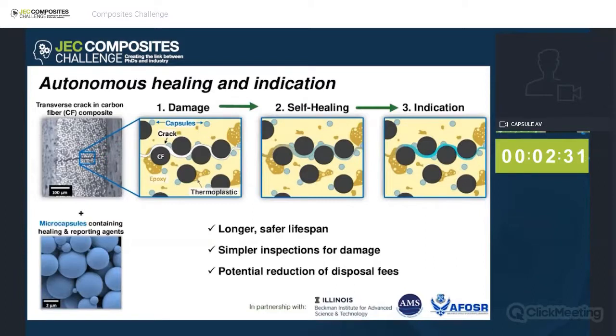From my slide, you can see that self-healing and damage indication begin immediately upon damage in this material system. As cracks propagate, the embedded capsules will burst and release their liquid cores. Then the released solvent will dissolve local thermoplastic, distribute it into the damaged areas, and finally evaporate to leave solid thermoplastic in place of the original damage. Meanwhile, the solvent is also transporting our special dye into the damaged areas, which will evaporate and finally allow the dye to activate in those healed areas. And this will make it significantly easier to see microdamage.